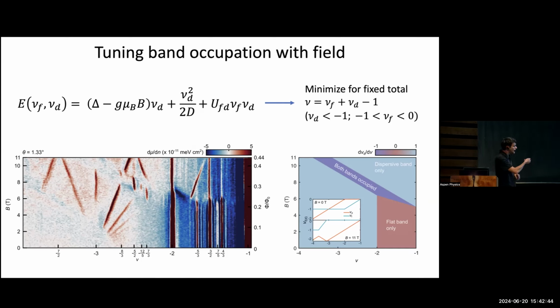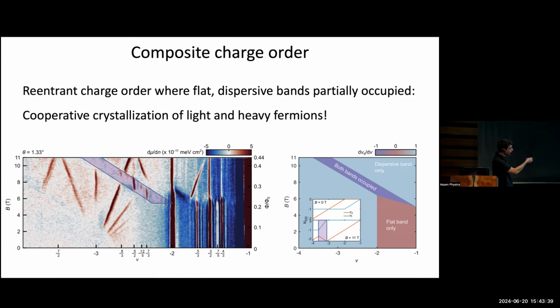If you go out here, again, once you've gotten to nu equals 2, if you just follow along your low magnetic field, you've completely filled both of the S bands. So now the only thing you can do is start to fill these P bands. These are more dispersive, and that explains what's going on in terms of the Hofstadter physics, that is, when you're occupying the flat bands, you tend to favor charge-ordered states. When you occupy the dispersive bands, actually you favor forming this Hofstadter type physics in a magnetic field. And then lastly, I mentioned there was this funny region here. There were a bunch of vertical states. Those, if you just look at where they occur, at the fractional values that they occur, it's actually the exact same fractions as we had over here, except modulo an integer. And what spit out from this very simple theoretical model is that actually in this regime, in this little purple regime here, you're occupying both bands.